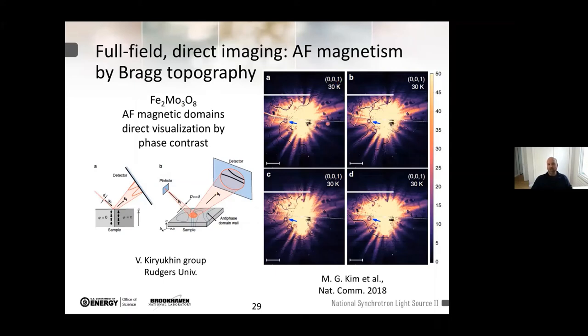And you see very well that if you cycle the temperature and you come back at the same temperature, as much as we did before, always the same recipe, you see that there are specific structural defects here marked with the blue arrow that are static in the image, they don't move. And you have wiggling things going around, that instead are rearranged each time that you go back into the magnetic phase. So evidently those, and we proved by calculations and simulation, are magnetic boundaries, antiferromagnetic boundaries that can be visualized directly in full field through the coherence of our beam.